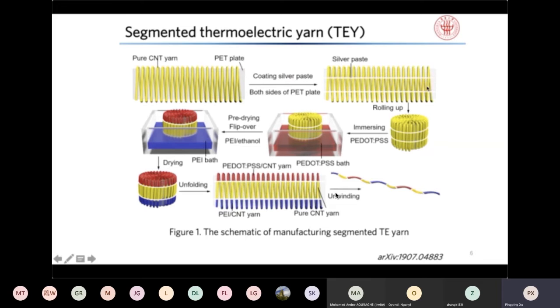So first we dip it into an ink with the p-type paste. The p-type paste is a conducting polymer with p-type properties, and then we dry it, flip it over, and soak the other side into the PEI solution. PEI solution can dope the carbon nanotube into n-type. And finally, if we unwrap the carbon yarn, we have this segmented structure. You have alternating p-type, n-type, p-type, n-type. Then we can use the thermoelectric segmented yarn to fabricate the thermoelectric generator.